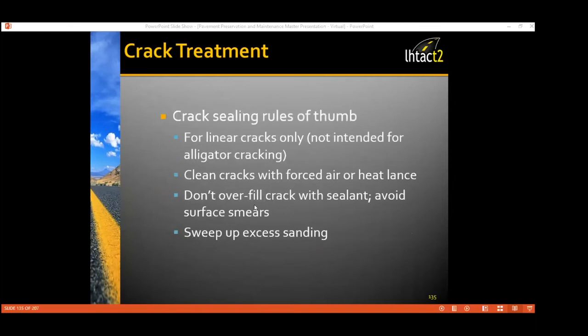So again, just some general rules of thumb for crack sealing. For the linear cracks only. It's not intended for alligator cracking. You're just throwing good money after bad if you're trying to crack seal the alligator cracks. It's your pavement that's shot. You're going to have to cut it out and replace the pavement. We want to be able to clean the cracks. I can't emphasize that enough. You want a really good clean surface that's dry. And so a heat lance will help us with that.